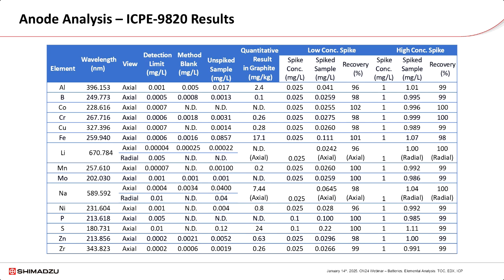By comparing the detection limits of lithium and sodium measured with two different views, we can easily see the axial view greatly increases sensitivity and lowers the detection limits. Spiked samples were also analyzed with both low and high concentrations with a spike recovery in the range of 96 to 102%, indicating great accuracy of the analysis results obtained by ICPE-9820.